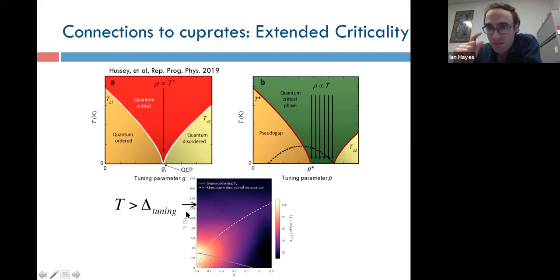You can see the main detuning energy, which gives you this fan-like region and some region of doping independence in the Hall response. Then there's some other energy or time scale that makes those fluctuations or the effect of those fluctuations in the transport non-zero all the way down to zero temperature. There's something that sustains the effect throughout this region. So that'll be an important avenue to consider in the future.